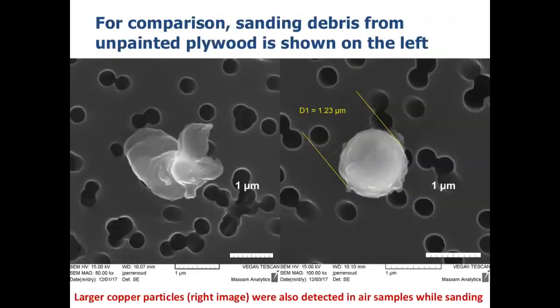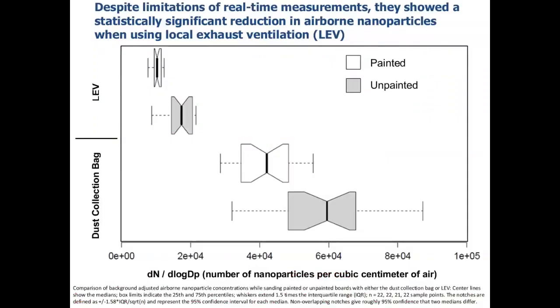For comparison, sanding debris from unpainted plywood is shown on the left, where the bright white specks of TiO2 are no longer observed. Larger copper particles, or this one shown here with a diameter around 1 micron, were also detected in air samples collected during sanding. Despite some of the limitations of the real-time instruments, they were able to show a statistically significant reduction in airborne nanoparticle emissions while using local exhaust ventilation. This is during sanding, and that's in comparison to the dust collection bag that came with the sander.